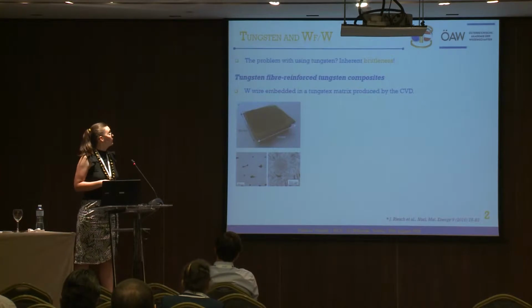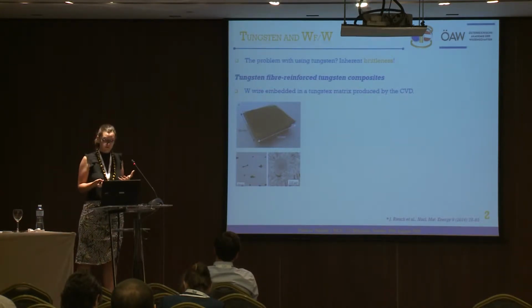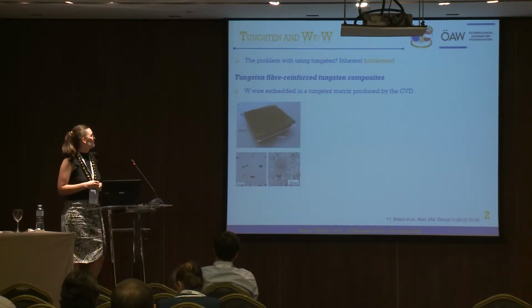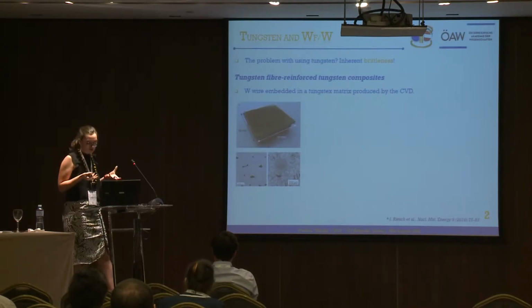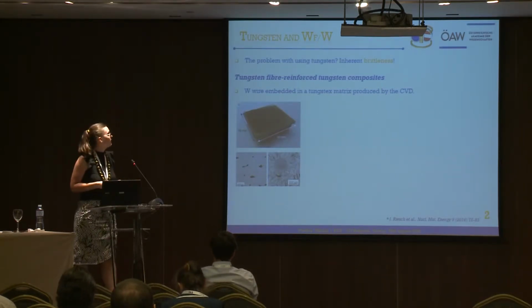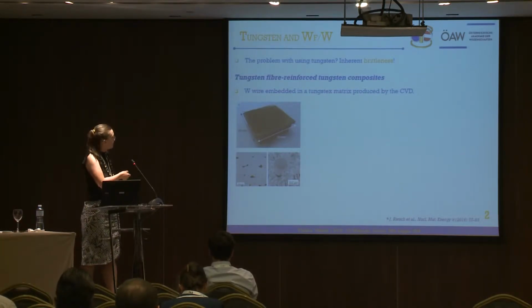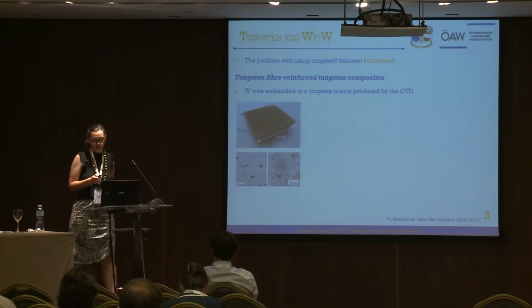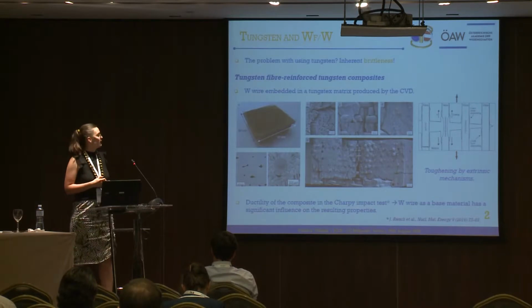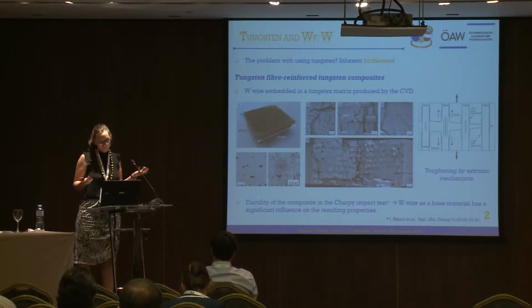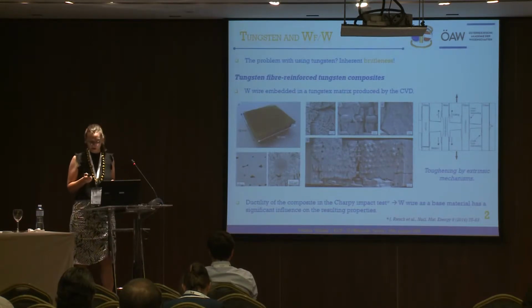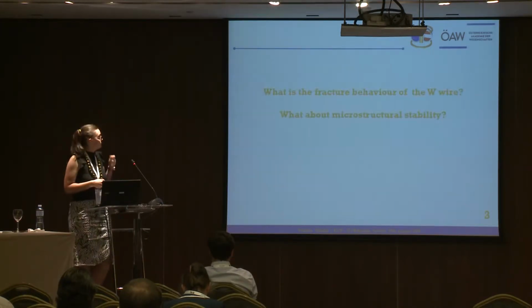One of them is building a composite material, tungsten fiber reinforced composite, where the wires from my title come into the picture. Essentially we take the commercially available fibers, and they are embedded in a tungsten matrix which is produced by a CVD process, and in such a way we can actually obtain better toughness results and better ductility.